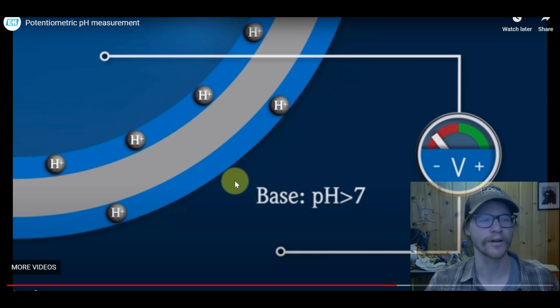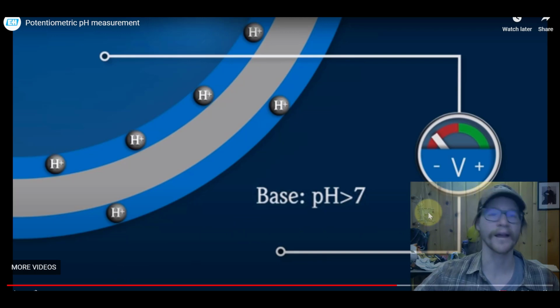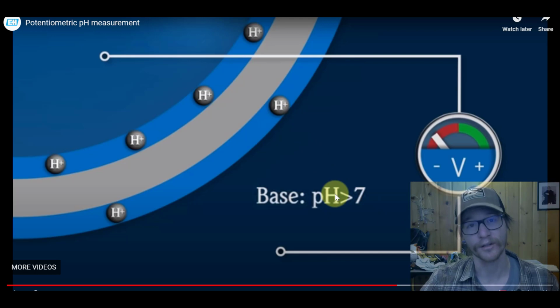So just know that pH meters are not going to be as accurate in very low pHs, especially below pH maybe 2 depending on the meter, but certainly below 1. So if you're talking about strong acids and you're trying to measure the pH, this outer layer is totally, completely saturated. Another thing to consider then is if you're trying to measure the pH of a solution that has other ions that are comparable in size and charge to hydrogen. It makes sense that the reason hydrogen ion can diffuse into this gel layer is simply based on the size of the tetrahedral sites that form in this partially crystalline silicate layer of glass. But if you have an ion that's comparable in size and charge, those are the only differential parameters that are preventing anything else from diffusing into this.